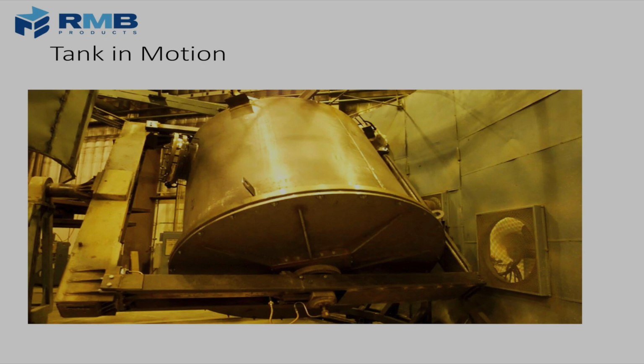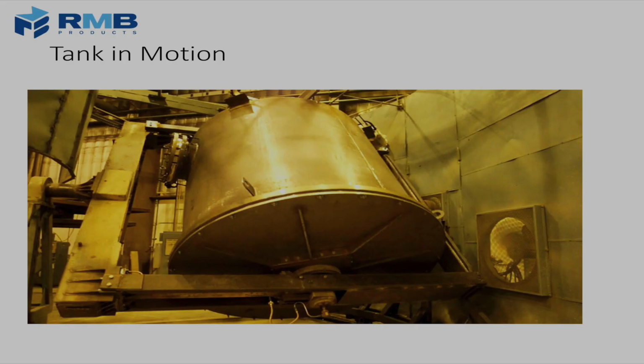In this case, this vessel has been preheated. So it's already hot. It's so massive that we need to make sure it's already got some of the temperature going. So we are very quickly going to be dropping the resin into the opening there using this hopper. And in this case, it's ETFE or Tefzel resin in granular form. And we pull it over, and it's just the right amount to get the thickness of liner that we're looking for. And we very quickly will pour that into the vessel. Once we're done, we close it back up.